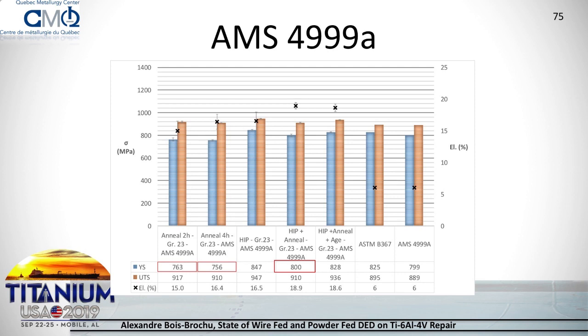With grade 23, you'll see yield strength that is below the required strength for annealing at this temperature, but as well if you do HIP plus anneal. Meanwhile, if you only perform the HIP, you actually obtain higher strength. This is most likely because the application of pressure prevents coarsening of a certain aspect in the microstructure. The alpha lath width is the same between both processes, but the beta interlamellar structure is much wider when you're only annealing than when you're only hipping.